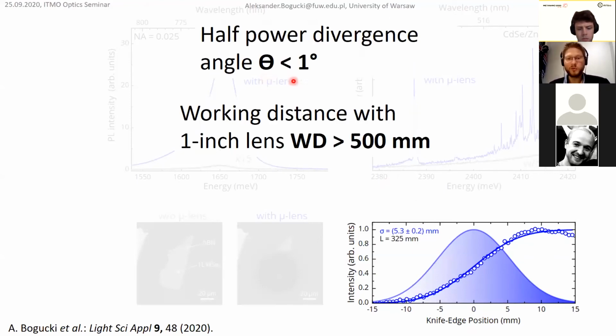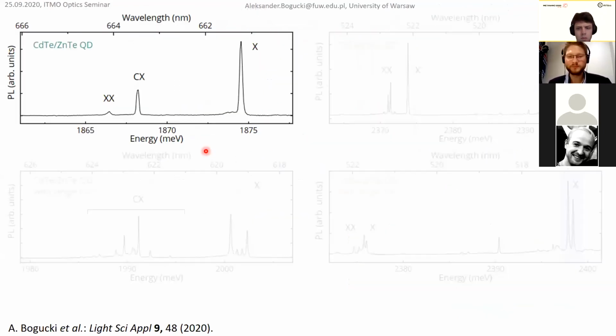So indeed, we obtained a half-power divergence angle below 1 degree. So this is ultra narrow emission from that quantum dot. So all signal comes into that angle, which we can translate to a working distance of half a meter, so 500 millimeters with a 1 inch collection lens. So we increased from 6 millimeters to 500 millimeters.